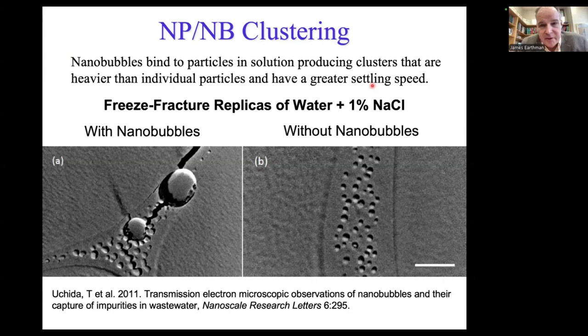Here are some freeze fracture replica images of some nanobubbles and nanoparticles that were published by Uchida and his group. And you can see here, this is for 1% sodium chloride. So these are sodium chloride nanoparticles here. And you can see that some of them are binding, or seem to be binding, to this nanobubble. This is without the nanobubbles. This is just with the nanoparticles, with the sodium chloride without the nanobubbles. So here you can see the nanobubbles, pretty clear distinction. And you can see the nanoparticles are binding to them.